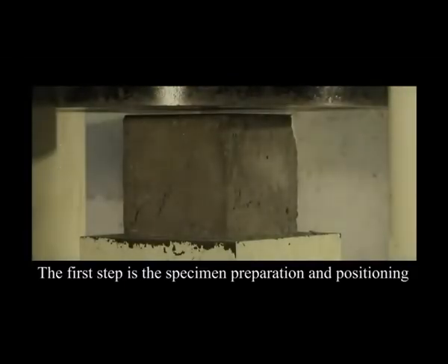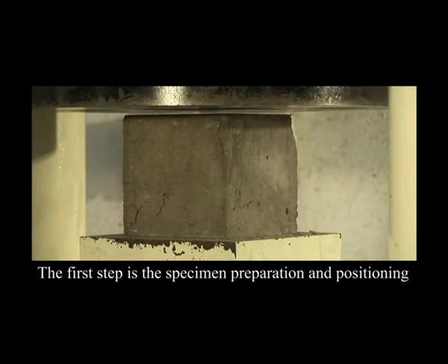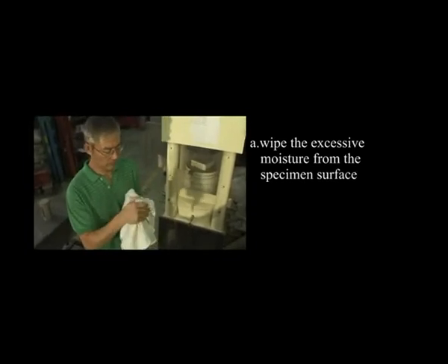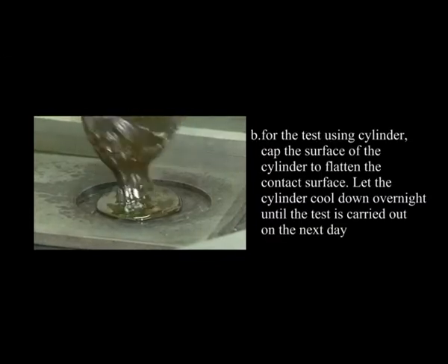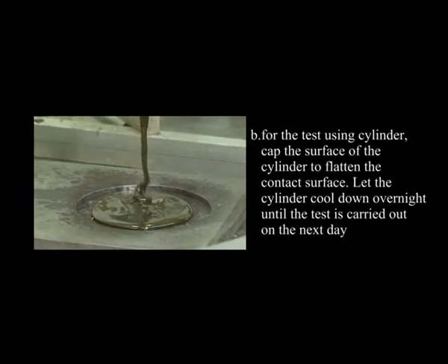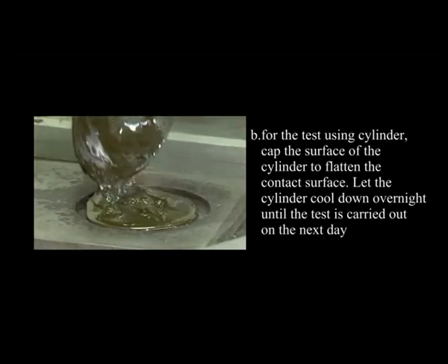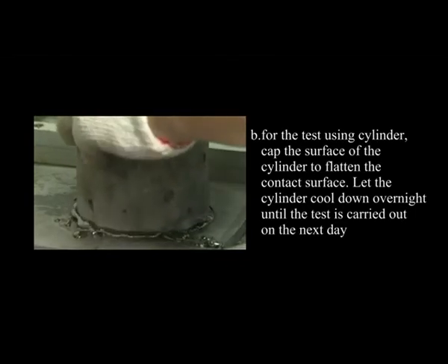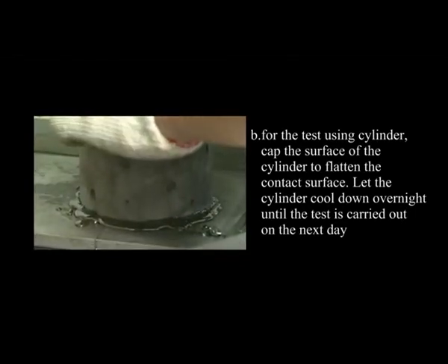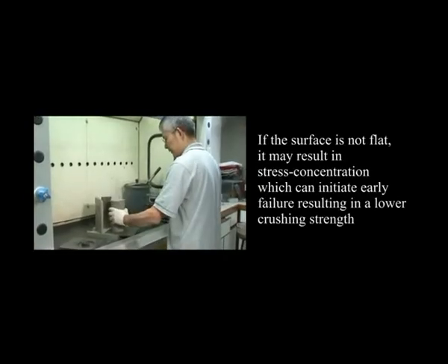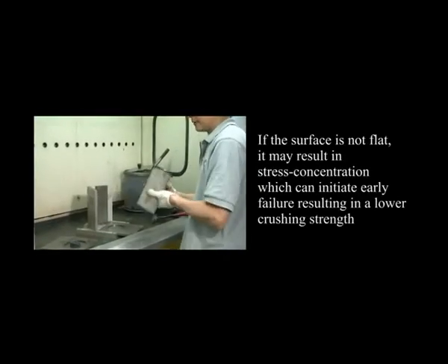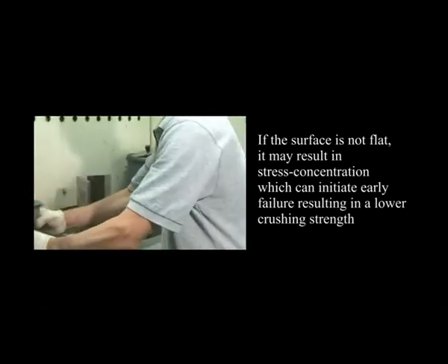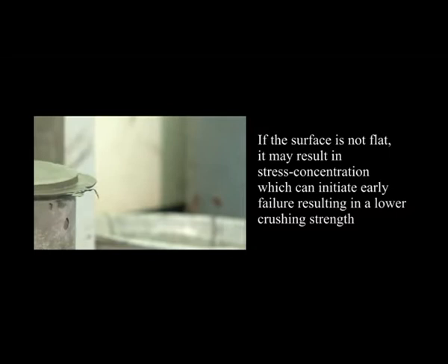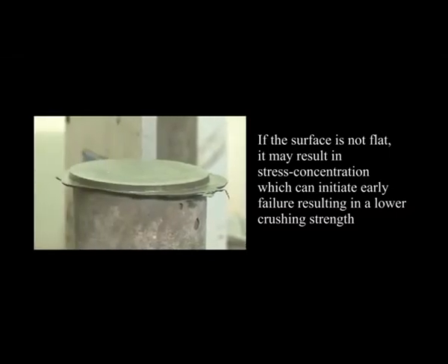1. The first step is the specimen preparation and positioning. A. Wipe the excessive moisture from the specimen's surface. B. For the test using cylinder, cap the surface of the cylinder to flatten the contact surface. Let the cylinder cool down overnight until the test is carried out on the next day. If the surface is not flat, it may result in stress concentration, which can initiate early failure, resulting in a lower crushing strength.